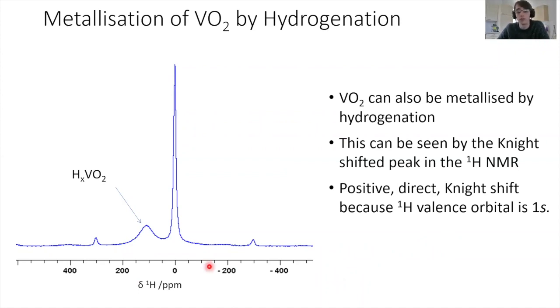The way you can tell that you've turned it into a metal is you get this peak appearing in the proton spectrum. This is around 100 ppm, which is well outside the diamagnetic range for protons. And this is a positive direct Knight shift, because the valence orbitals on the protons are s orbitals, the 1s orbital. And by doing variable temperature experiments, I could show that this was temperature independent, and therefore this was a Knight shift and not a paramagnetic shift.